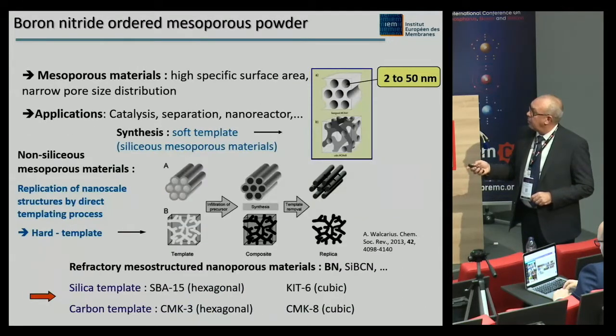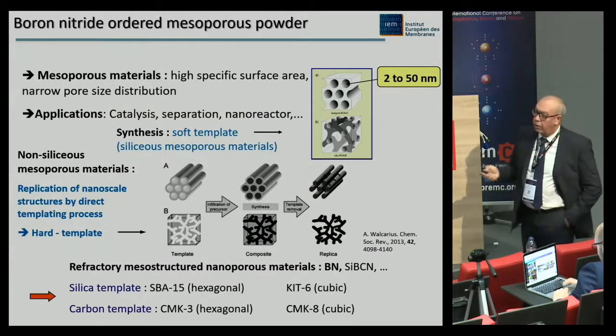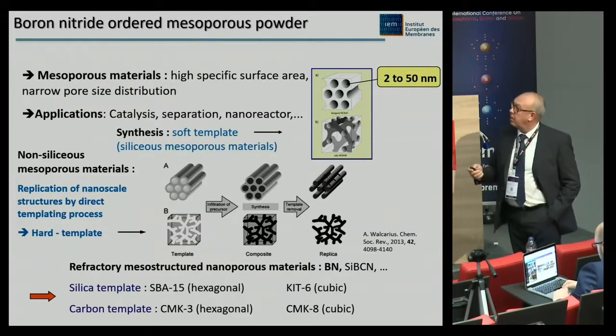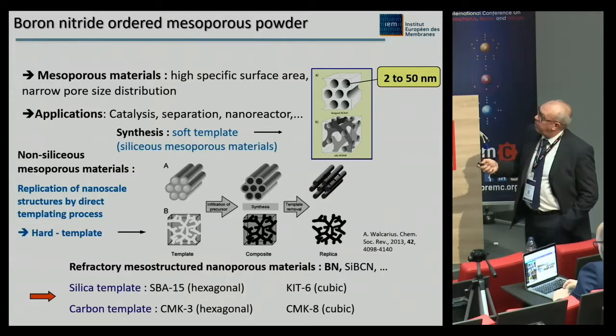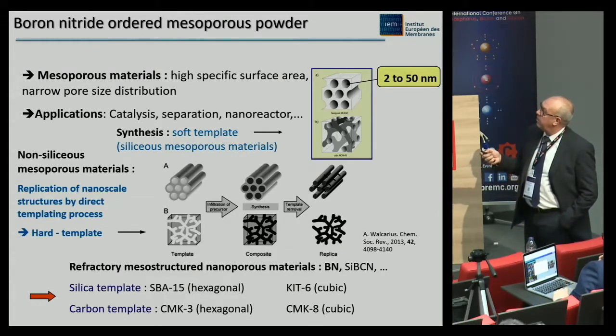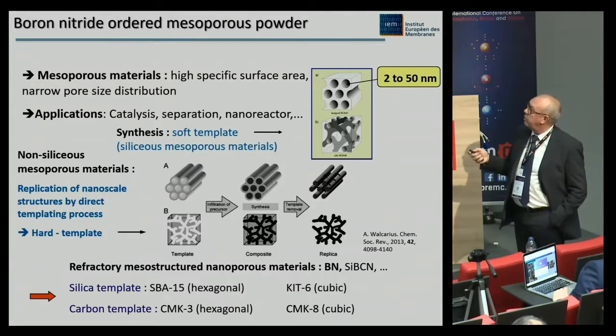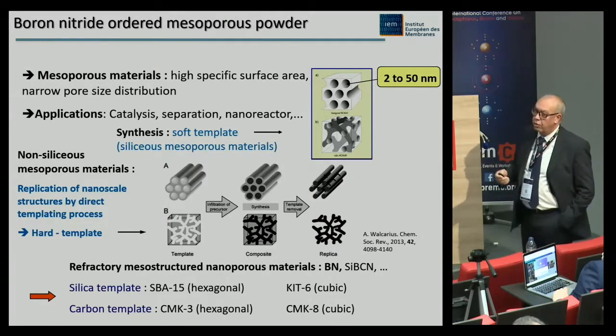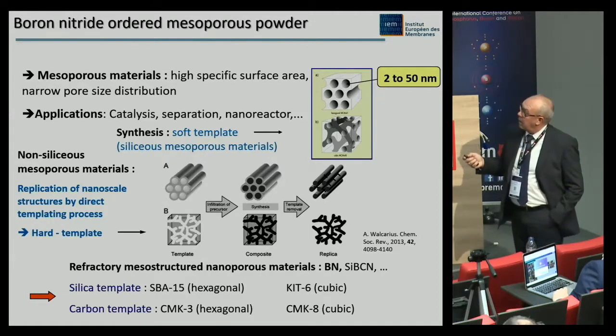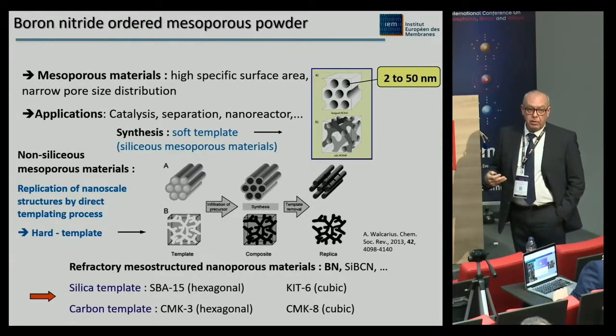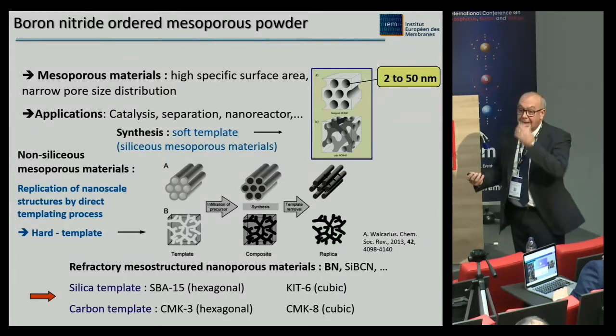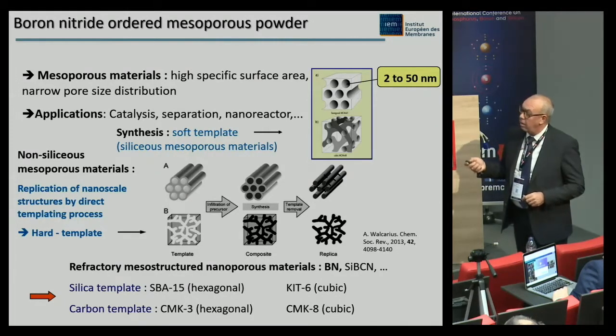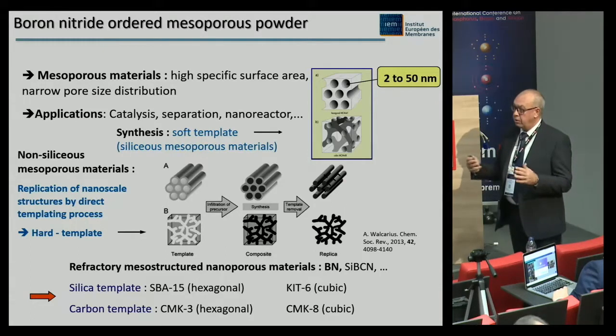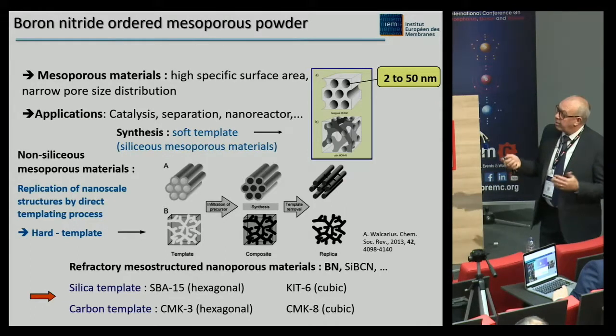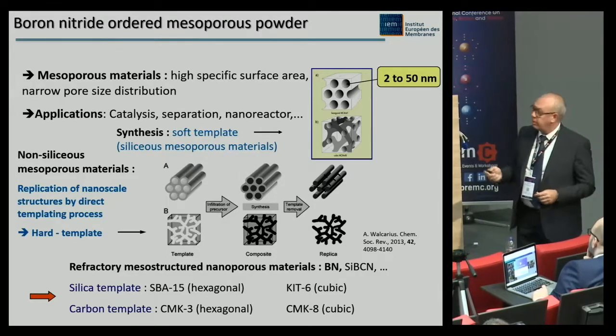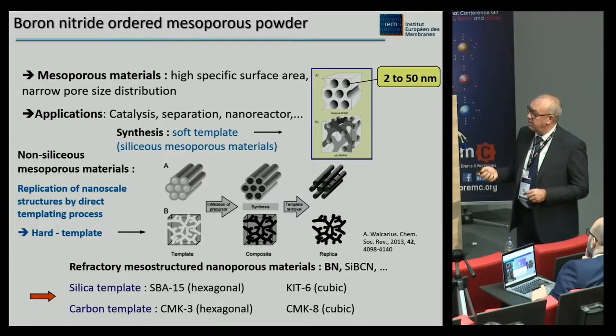So if I go now to another example, the porous materials, particularly the mesoporous materials, they display a high specific surface area and a narrow pore size distribution. The pores have dimensions from 2 to 50 nanometers. And if you want to prepare these materials, for example in the silica system, it's relatively easy to do that using a soft template route in solution by self-assembly. But if you want to prepare the same kind of materials in the non-oxide system, it's very difficult.